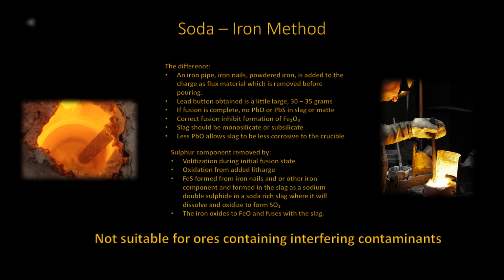Gold is not soluble in a ferrous alkaline matte, and silver will dissolve to a very limited extent. This method is not suitable for those ores that contain contaminants that tend to interfere with the fusion. Any sulfide ore that contains copper, tellurium, nickel, antimony, cobalt, or arsenic should not be treated using this method.